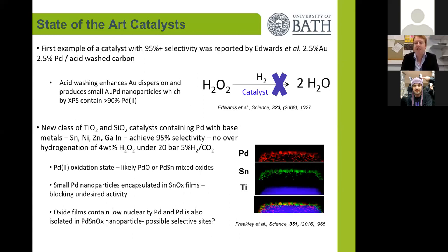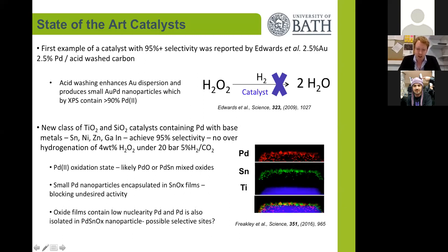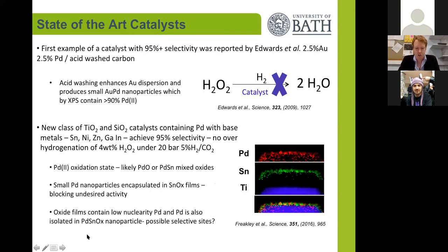This shows that the effect is not unique to gold and it's about controlling the speciation of the palladium. In these catalysts, the palladium was also in the Pd²⁺ oxidation state. The small palladium-rich nanoparticles were encapsulated by tin oxide layers, which formed very neatly on the edges of our titania, as seen in this EELS map. These oxide films contained low-nuclearity palladium, isolated in larger palladium-tin oxide particles. So here we've got some hints of what might be the possible selective sites.